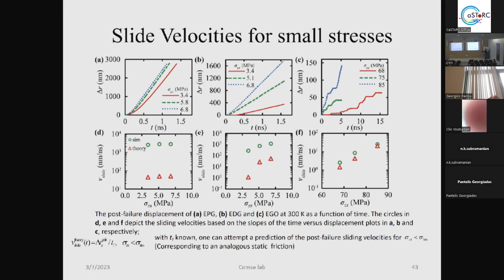Exactly. The theoretical value of the velocity, because here you can see the velocity, and the green are from the simulation, and we have these big errors, this big distance, let's say, of the value, because they're totally swimming. It was amazing. And we saw some other papers that are exploring other problems, but with graphene as interface, and they show also this, how can I say that, the zero adhesiveness, that the graphene doesn't cooperate with the rest of the polymer matrix. And also some colleagues from the group also showed that, also in PMMA, I think.